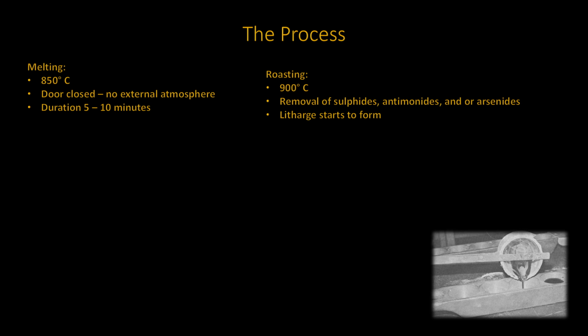After your concentrate or sample has been pulverized to 100 mesh, it must be thoroughly mixed with the flux material that is added. If it is not done, the scorification will fail. It is then placed into a furnace at 850 degrees centigrade for 5 to 10 minutes with the door closed, and any inlet to the outside air must be closed off. During this initial step, the lead should start to melt without oxidizing.